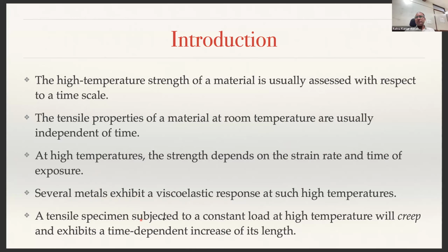So, for example, if you have a tensile specimen subjected to a constant load at high temperature, then what happens? It will creep. Meaning you take a specimen, apply a load, and hold the specimen at that particular load. If this test is done at room temperature, the stress will remain constant. What do I mean by that? Suppose this is my stress and this is my time, and I am doing this test at room temperature. I have applied some strain, because of which the stress has increased to that level, and then at that level of stress and strain, I have held the specimen.